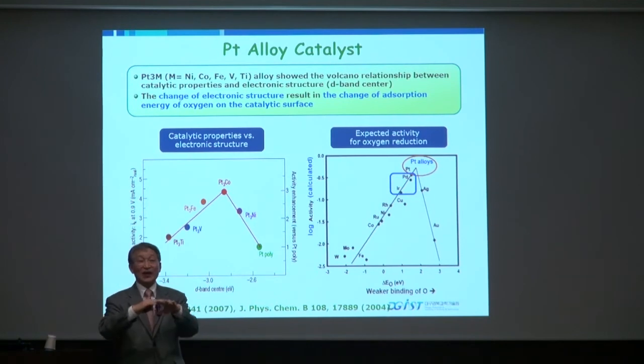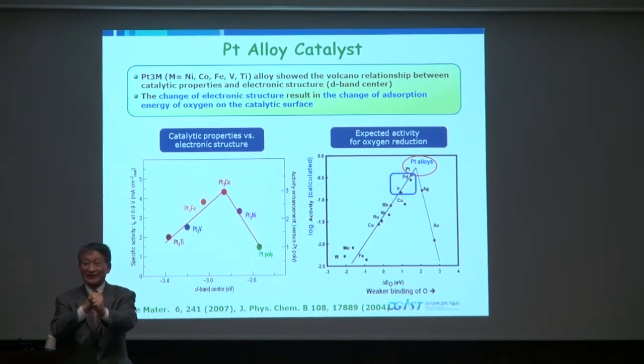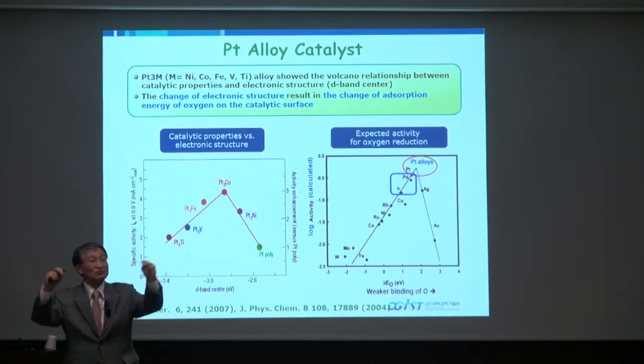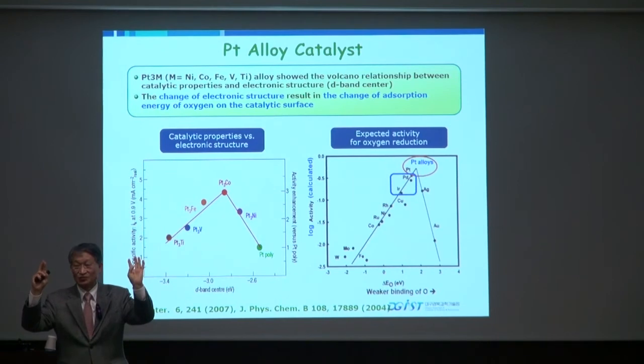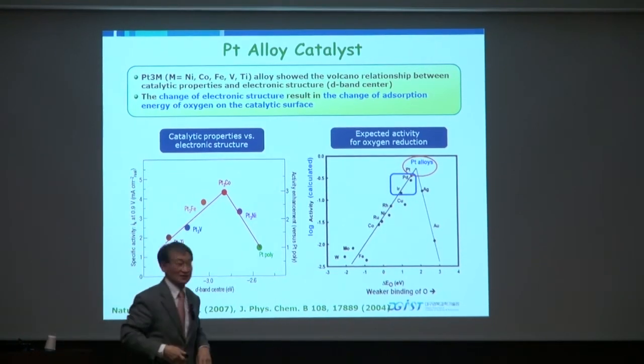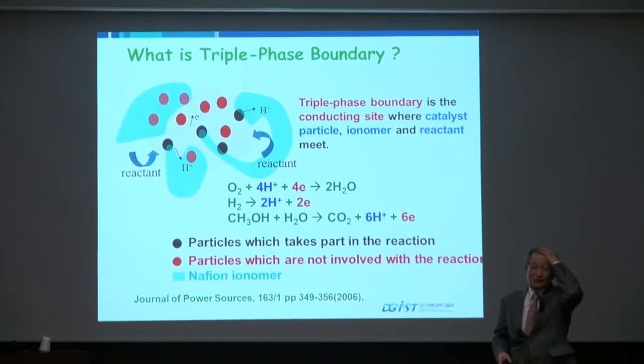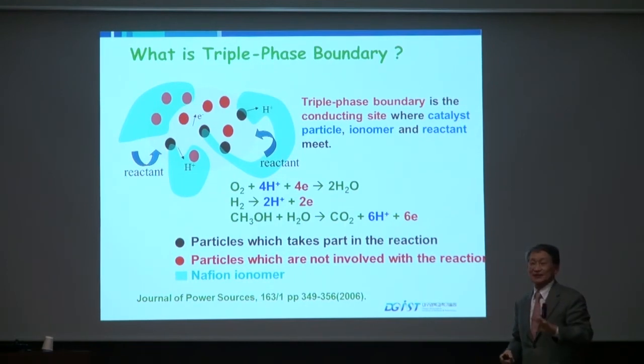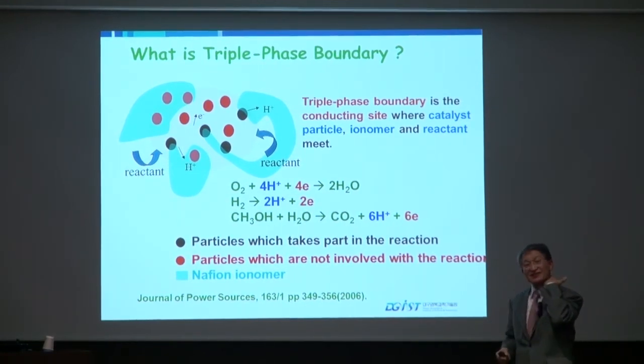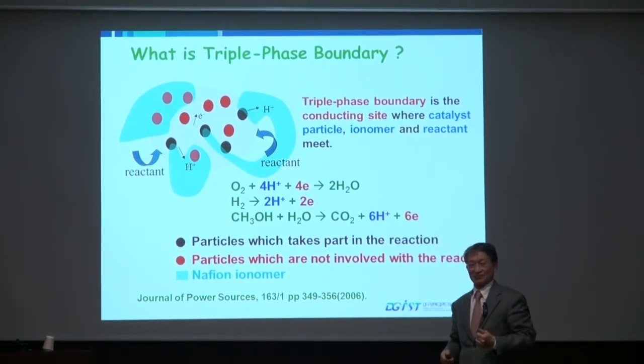So you have to have suitable binding energies, strong enough for chemical reactions, but weak enough for removal to refresh the catalyst site. Okay, the triple phase boundary. This is very much catalysis 101 class type things.